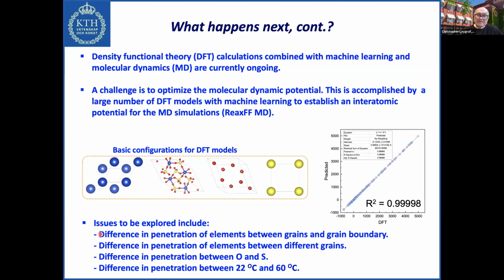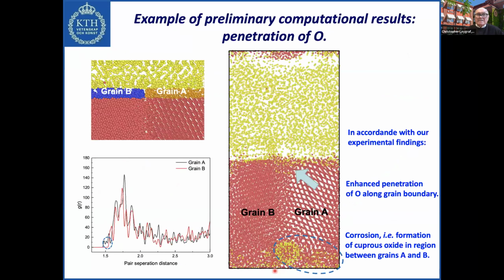So we can say that all of these results so far are preliminary, but we want to explore by this the difference in penetration of elements between grains and grain boundary, the difference in penetration of elements between different grains, the difference in penetration between oxygen and sulfur, and the difference in penetration between 22 and 60 degrees. All of this, again, to get a better view on why we get such a big difference between 22 and 60 degrees. So the final slide here shows an example of some preliminary computational results.